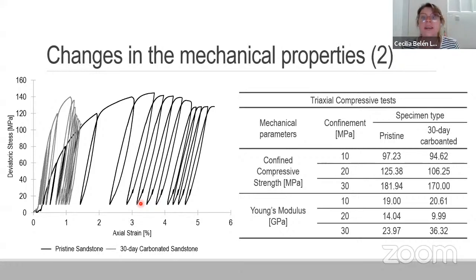When we analyzed the triaxial compressive tests performed, we also observed a reduction in the strength of the specimens when we aged them. But there was a difference between the behavior of the Young's modulus in this triaxial compressive test and the one presented in the uniaxial compressive tests.